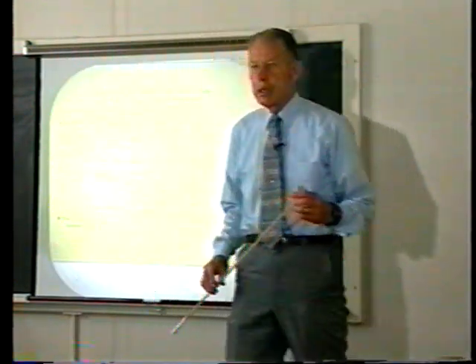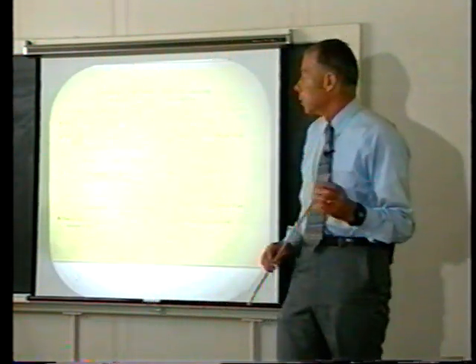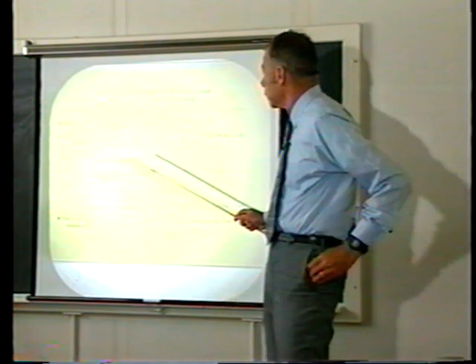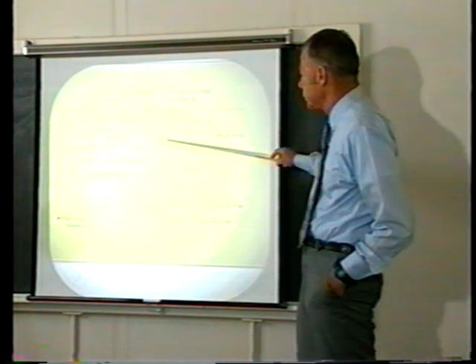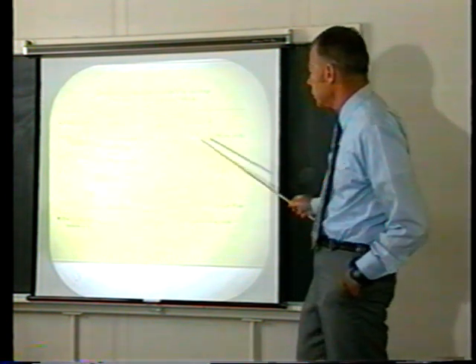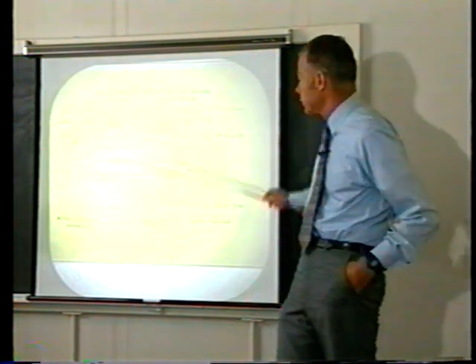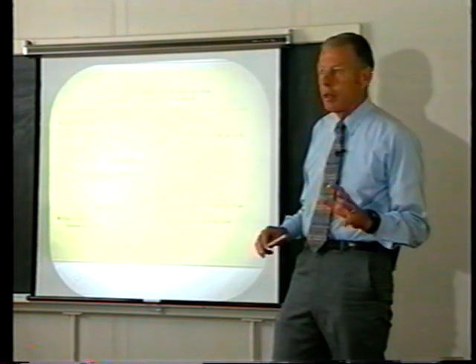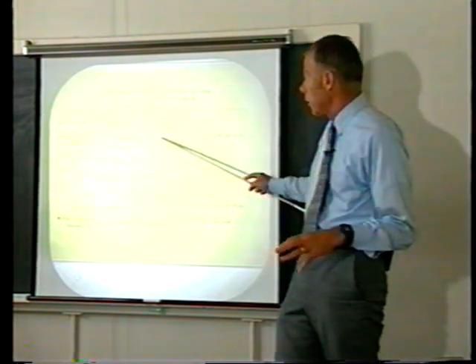And this is the only boron experiment that we ran where there was no excess power effect. In one of the palladium boron experiments, we collected the electrolysis gas and analyzed for helium-4. We found an excess helium production of 5.6 times 10 to the 13th atoms per 500 milliliters of the D2 and O2 gas that we collected. This is after we subtract off the background. There's always a background level of helium.